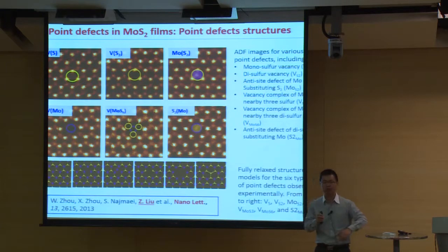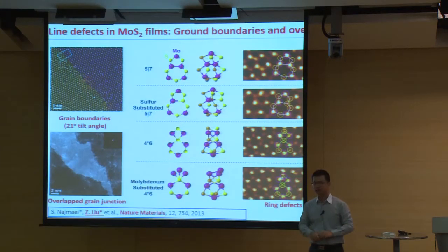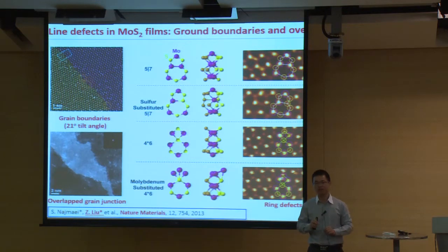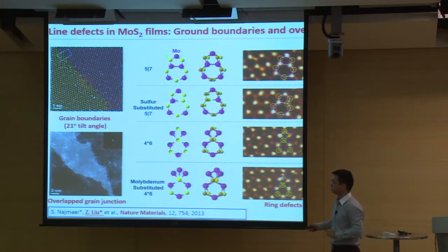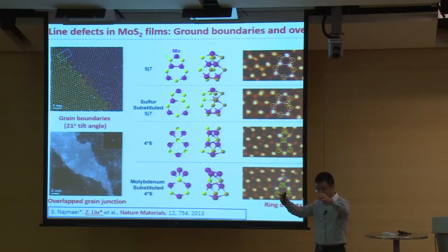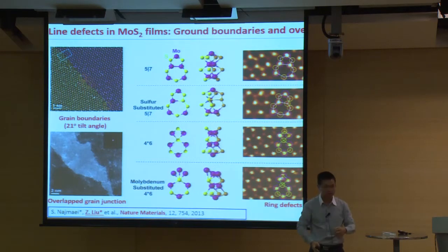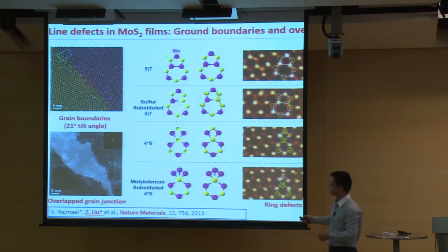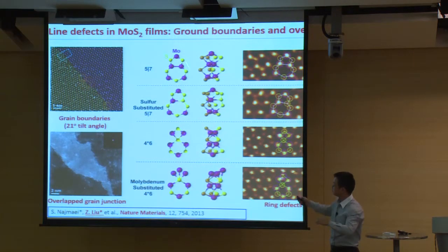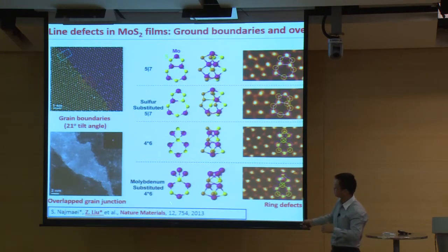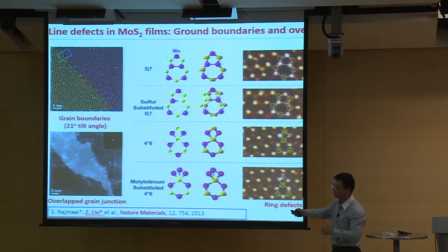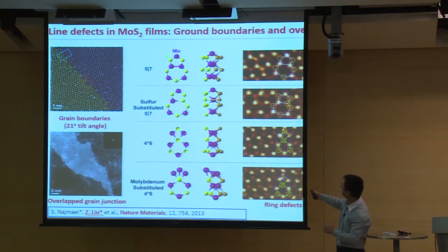And one thing I would like to mention here is this defect actually is a potential active site for catalysts. So if we can control the density of this defect, probably we can get a high performance catalyst material using the molybdenum sulfide. Okay, so next we move to the line defect. So in this material, we have observed 2 kinds of line defect. The first one, if 2 molybdenum sulfide domains grow bigger and meet each other, they will form grain boundaries, like graphene. Actually, because of the 3-layer molybdenum sulfide, we have a lot of variations. Here we show 4 different ring structures along these grain boundaries,